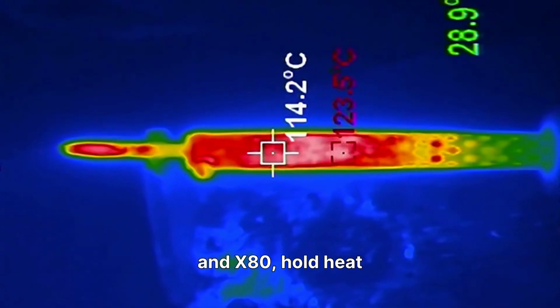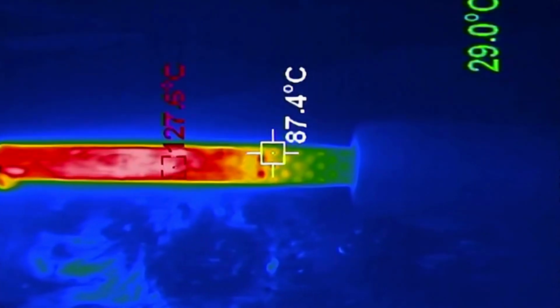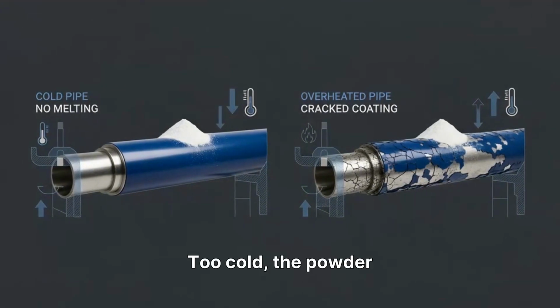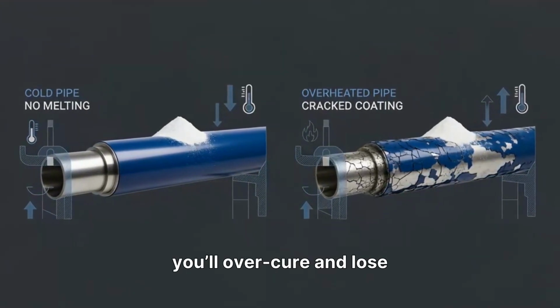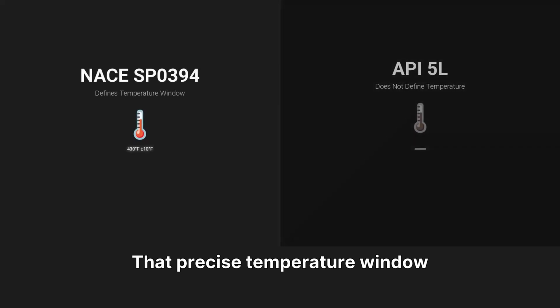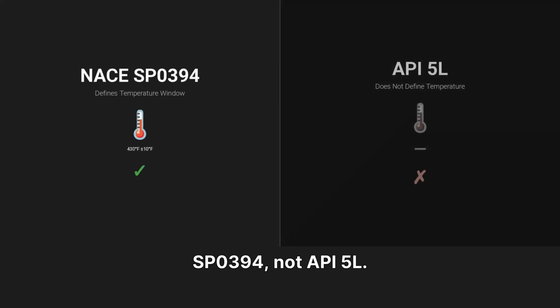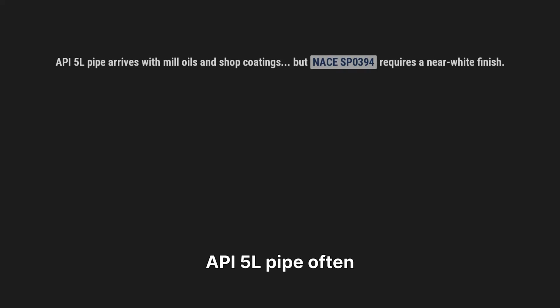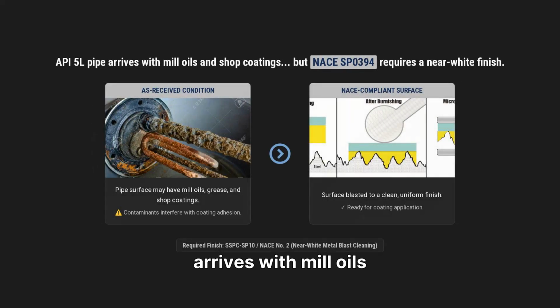Higher grade steels like X70 and X80 hold heat differently, which is critical during coating when the steel is preheated to around 430 degrees Fahrenheit for proper fusion. Too cold, the powder won't melt. Too hot, you'll overcure and lose adhesion. That precise temperature window is defined by NACE SP0394, not API 5L.